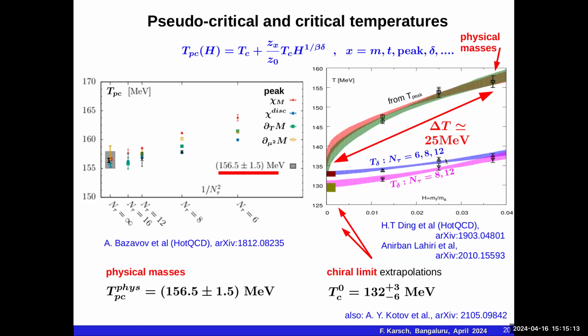So when I calculate as a pseudocritical temperature the value of the susceptibility at 60% of its peak height, it has a very weak quark mass dependence and allows for a rather quick and easy extrapolation to the chiral limit. So the outcome of such studies for QCD is that when one is at vanishing values of the quark masses, then one can extrapolate from the situation of physical light and strange quark masses to the chiral limit, and one finds that by going from physical masses to the chiral limit, the chiral phase transition drops by about 25 MeV, which, as you will see, is a rather big effect for QCD.